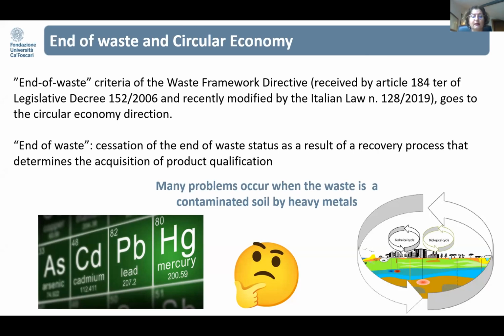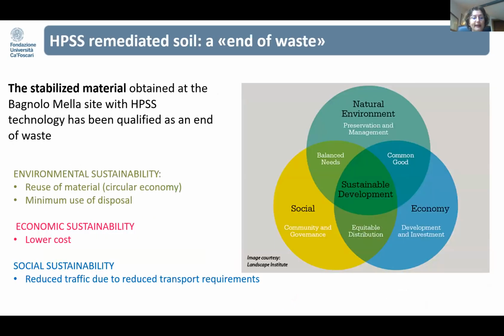But much more than this, the authorities certified that the treated material is an end of waste that can be used also for other applications, such as inert in the concrete formation. And as some of you already know, the HPSS, that means high performance stabilization solidification, is already a consolidated technology applied since 2006 in more than 15 contaminated sites. And I already presented at Remtech Europe in 2013 the evaluation of the sustainability of this technology.